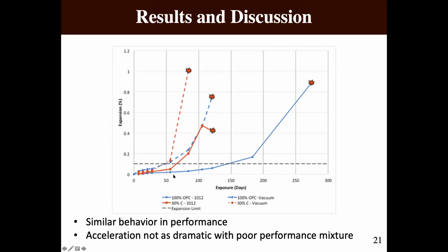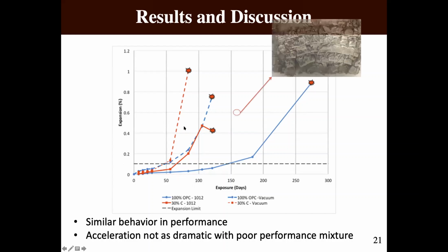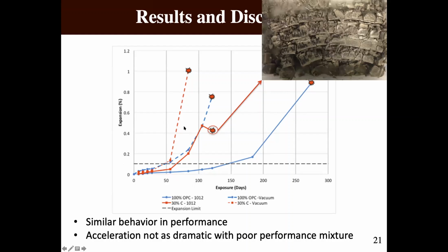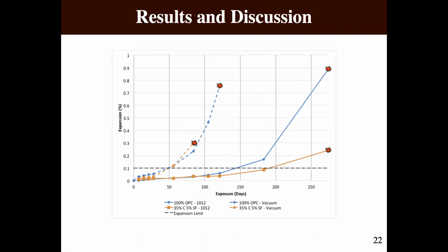When we look at Class C, while the 10-12 was pretty aggressive alone, because Class C is a very poor performer, we still saw a dramatic increase from the vacuum saturation test, right? And so when you look at Class C again, when you get to pretty expansive and aggressive solutions, particularly for Class C, you almost get a complete mush consistency of these bar samples. So it's very difficult to even measure these bars after a period of time.